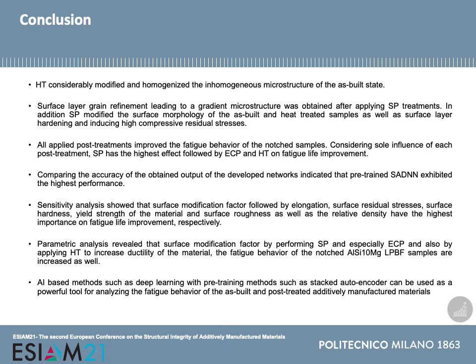About the results of the neural network modeling, comparing the accuracy of the obtained output of the developed networks, it was obtained that the deep neural network with pre-training in the stacked autoencoder has the highest performance. Also, sensitivity analysis showed that surface modification factor, followed by elongation as a factor of ductility, has the highest importance on fatigue life improvement, respectively. In addition, parametric analysis revealed that by modifying the surface through shot peening and ECP, and also by applying heat treatment to increase ductility, the fatigue behavior of the material can be increased as well.